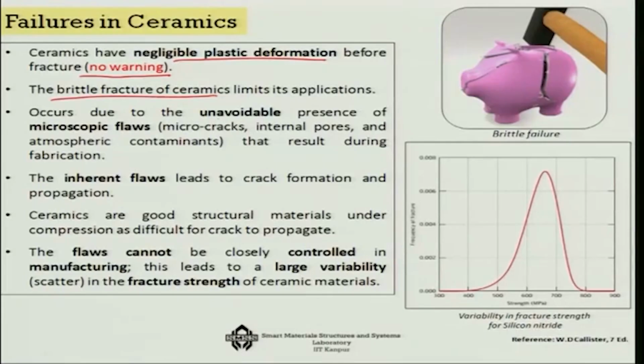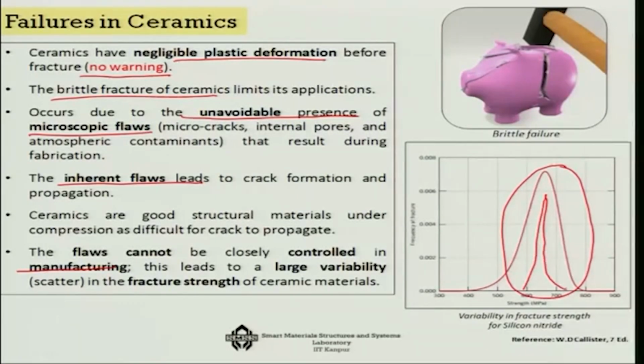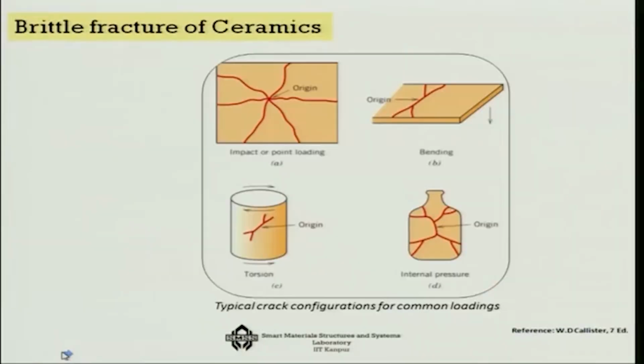And this occurs due to the unavoidable presence of microscopic flaws or micro cracks in the ceramics, and these cracks are unavoidable because these are the inherent flaws that are there in the systems. So, in order to have a ceramic with a high strength, you need to control these flaws during the manufacturing, and if you cannot control it, what you will get is this kind of a strength variation. So, this will become sharper and sharper as you can control it more and more. In fact, for metals you will get almost what we call a crisp probability. I told you, a straight line scenario. That is why the manufacturing process is so important in the ceramics.